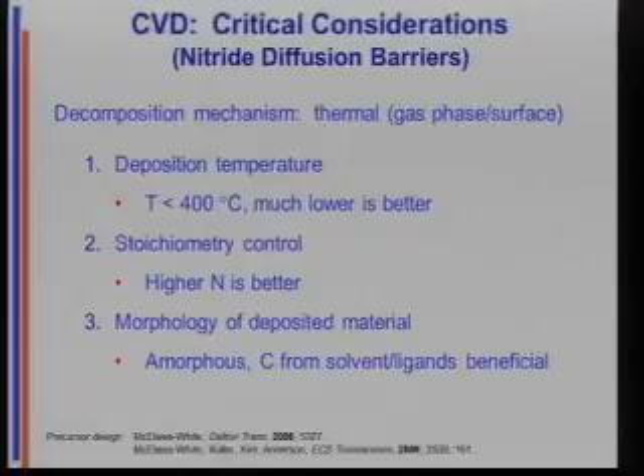You need to be able to control the stoichiometry of the films for materials reasons. And interestingly enough, for this particular problem, you want to grow amorphous material. And that's because for diffusion barriers, if you have polycrystalline material, the mechanism for failure is migration of copper along the grain boundaries. And so if you have crystallites, you want to have amorphous stuff in between them because it stuffs the boundaries and blocks copper diffusion. So you really want to grow amorphous stuff. And that means that if you have carbon depositing in your material, for this particular application, that's a plus. If you want to deposit from organometallics, people always say, you're going to get carbon in your stuff. Well, if you pick your problem carefully so that that carbon is an advantage, you're going to win. Okay. So the carbon's fine. All right.